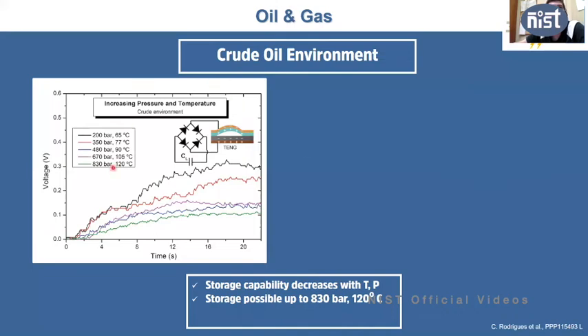So we have also shown that we can charge different capacitors at different pressures. We can go from 200 bars at 60 degrees up to 800 bars at 120 degrees, and you can still charge capacitors at these high pressures and these high voltages.